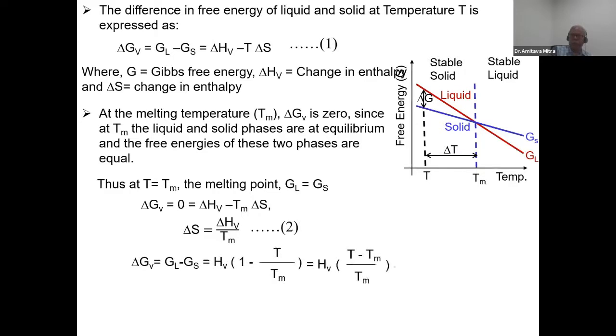So if we replace this in equation 1, we get the equation delta Gv is equal to Hv times (T minus Tm) divided by Tm. So this is an equation, and this is a very important parameter, delta T. Now what is delta T? It is the temperature we are concerned with, minus Tm, the melting temperature.